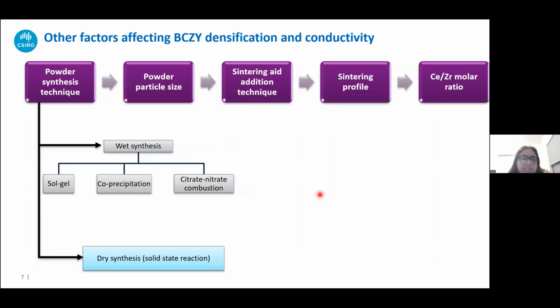So one is the wet synthesis technique, where all the precursors are added in a liquid solution, and then it can be either a sol-gel method, or a co-precipitation method, or even the Pechini method. Or it can be dry synthesis, where all the powder precursors undergo thermal treatment in the powder form itself, and then the phase evolution takes place.